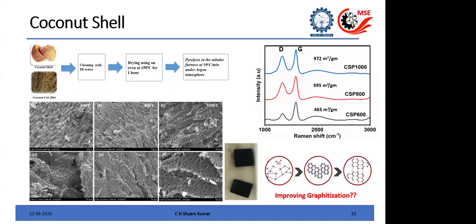So how to do that? One way is that if you increase the temperature more, definitely, as I told, the more stable one is sp2 carbon. So sp3 will transform to sp2, maybe at more than 2000 or 2500. These carbons are very stable in an inert atmosphere at very high temperature. You can even heat to maybe 3000 degrees Celsius, and they will still be stable. This is one way to increase the sp2 content, but you are limited by the experimental constraints.